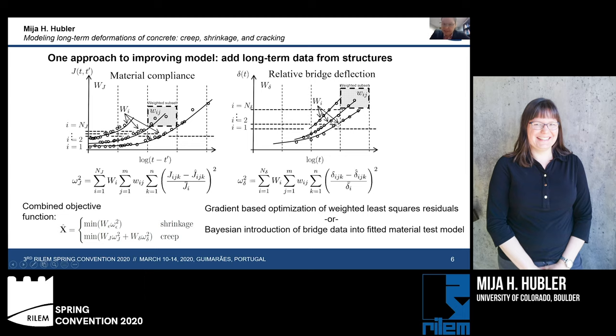Now we can combine these two data sets very carefully. First, by creating weighted subsets of the data depending on the input of the particular type of experiment or the field observation of the bridge. Then when we have the weighting of the data with respect to its input values, we can create a combined objective function, minimizing the error between the data and our prediction equation, both for the shrinkage and the creep. There are multiple ways that we can minimize this objective function. One of them is in terms of optimization or machine learning or learning types of approaches. The only real difference between optimization and learning is whether or not we incorporate the uncertainty in our prediction process.